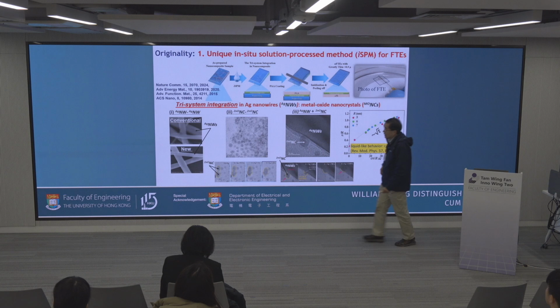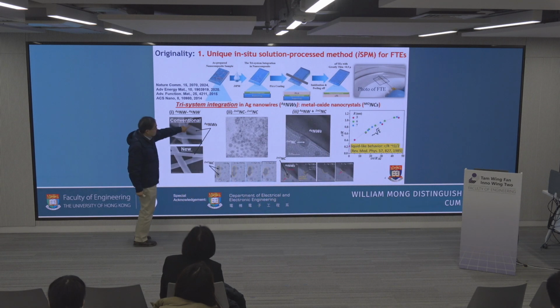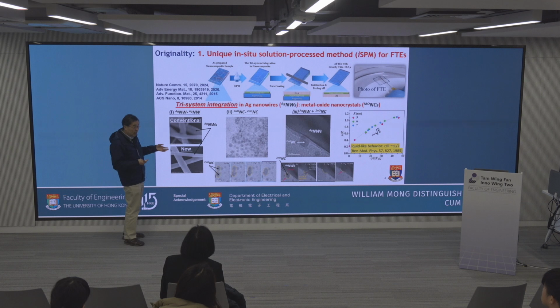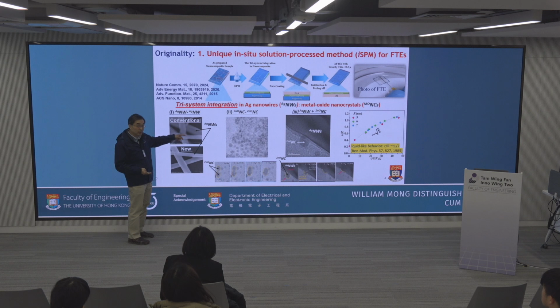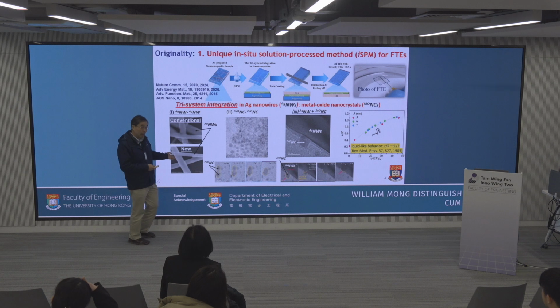You can see from the SEM the surface of the silver wires. All of them, no matter whether you buy them or synthesize them yourself, always have some insulative ligand protecting the nanowires. That's why they can be stable. Otherwise, they will aggregate and merge together, no longer useful, just like Chinese noodles at the very beginning. But with our approach, we can eliminate all the insulative jacket, promoting the coalescence of the silver nanowires at the joints. The atoms are integrated together, no longer individual wires. They become a silver net, like a fishing net, more stable and more conductive. That is number one.